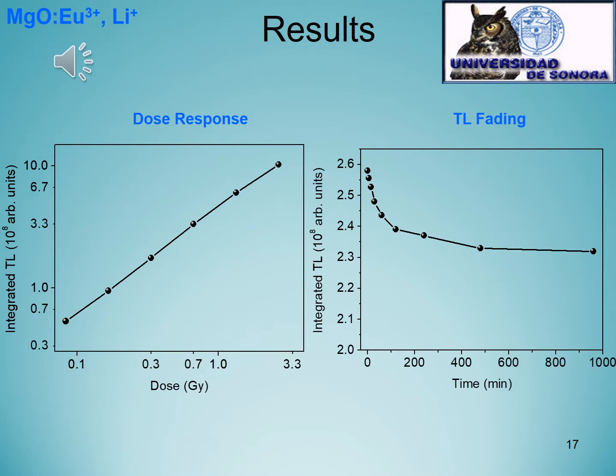We could obtain a linear trend on the dose response curve, which is a very good calibration curve of the material. It is desirable to have a linear trend, and we couldn't see, supported with the previous figure, any saturation evidence.